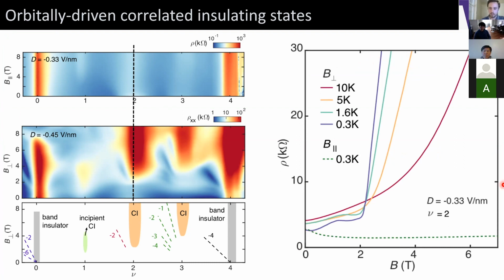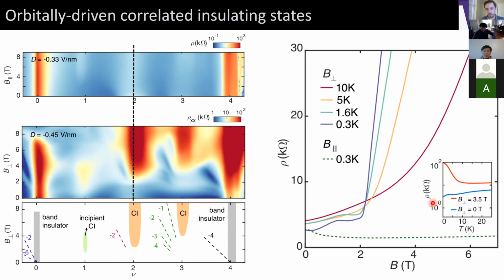We can realize that this is really seemingly a first order phase transition between a metallic phase at low magnetic field, which has weird but approximately metallic temperature dependence, where the resistivity shrinks as we lower the temperature. And in contrast, at high field, say at 3.5 Tesla, we see a more canonical metal insulator transition as we cool the system down. So this behaves like a metal below the critical field, and this behaves like an insulator as a function of temperature above the critical field.